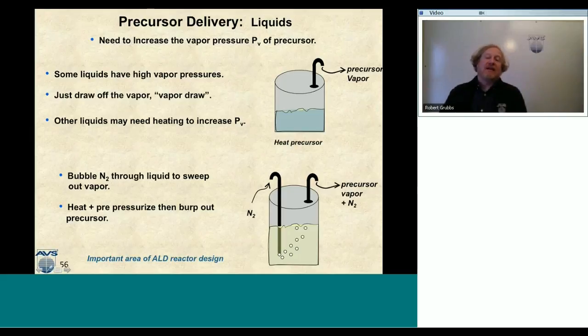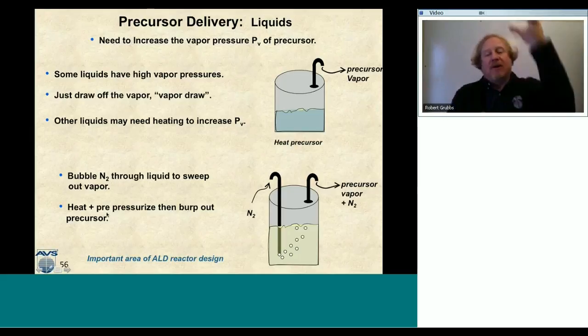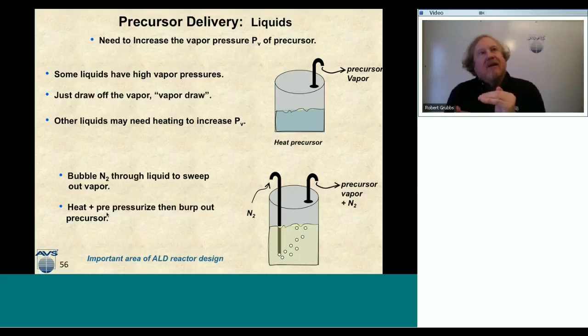Another method is that you can heat the ampule, and then pre-pressurize it with nitrogen up to maybe, I don't know, 20 psi, and then let it go, and you'll get this rush of vapor that comes out of the precursor container and into your reactor. So it's sort of like pre-pressurize it and then burp out the precursor. And so precursor delivery is still a very important area of ALD reactor design, just because of the myriad possibilities of ALD precursors. We really need to be able to deliver them successfully and without particle generation.